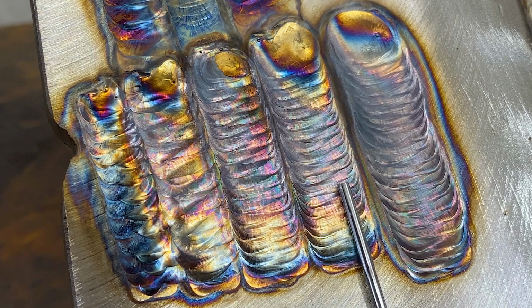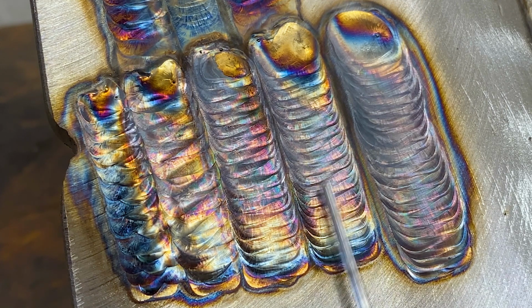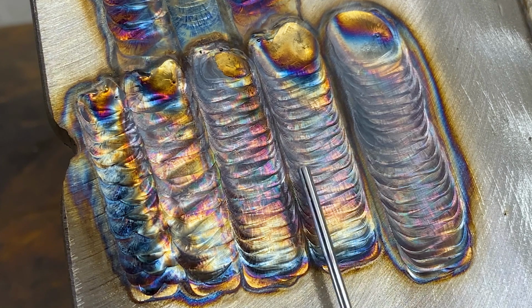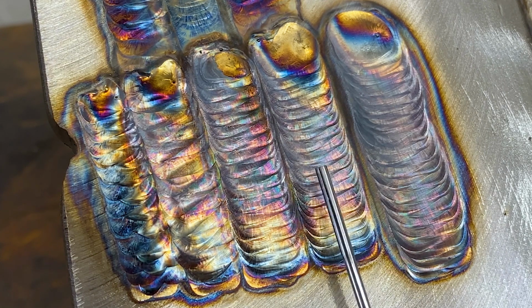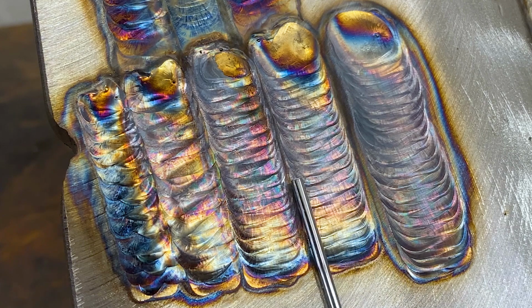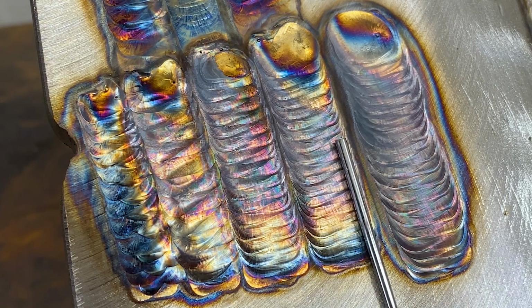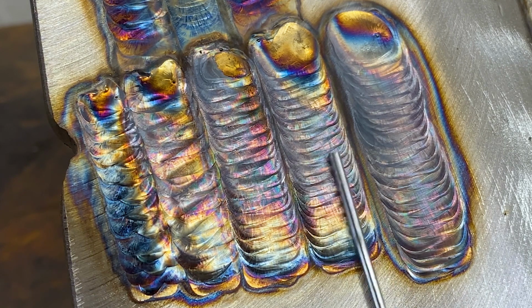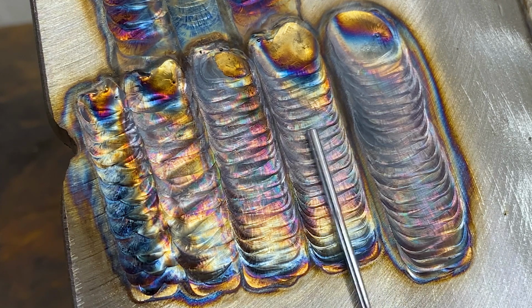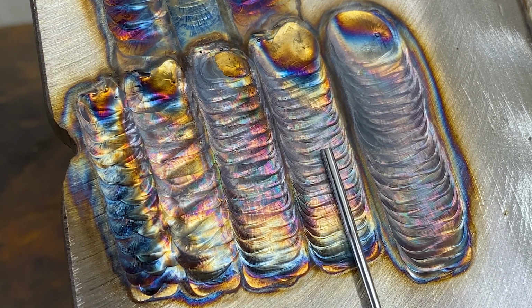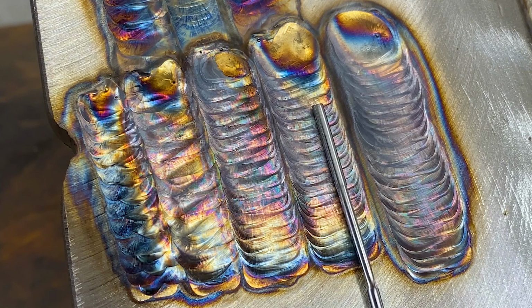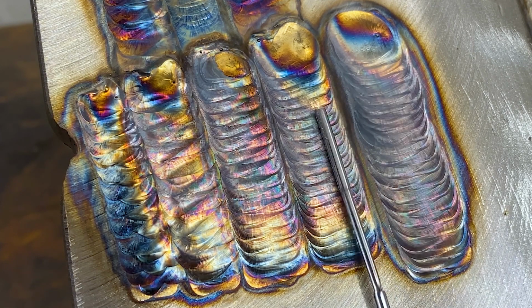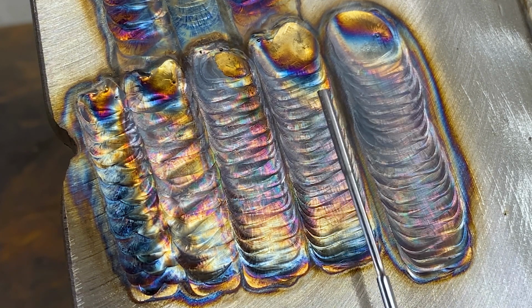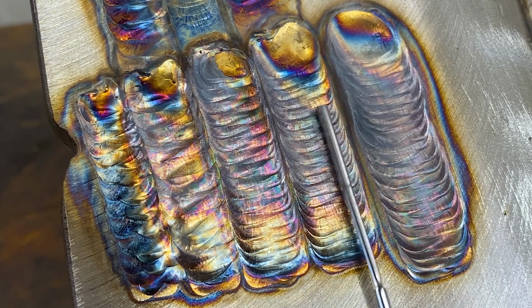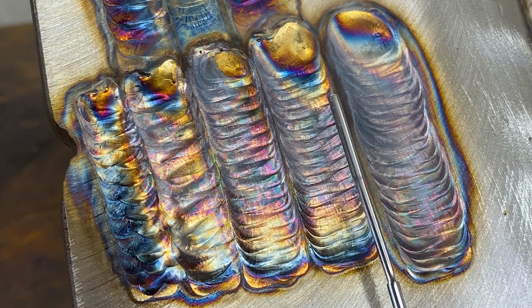Going further, I stepped it up to 170 amps, running same filler, same everything. The puddle started getting erratic. It was hard. So what I mean by that is in the side-to-side transfer, as the weld solidified, so you'll watch it cool and then chase back, cool and then chase back. It was very quick and it was shaky, right? That's telling me that I'm getting too hot. It's still an okay weld. It's probably out of the 5, it's the second best, but you're pushing the envelope on what the metal can take.